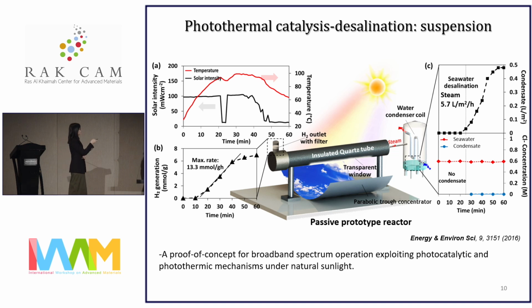And here shows the outdoor real sunlight conditions performance. And the time-dependent study of the solar intensity and reaction temperature shows that despite the fluctuation of solar intensity, we could obtain a fairly stable and high hydrogen production. And of course, at the same time, steam can be produced at about 6 liters per meter square per hour. And again, here the absence of chlorine ions in the condensate indicates the production of fresh water.